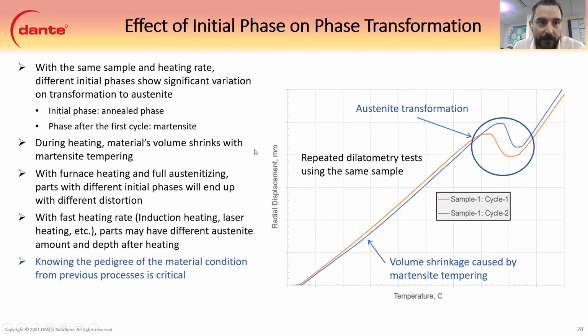And so during this, the initial phase was an annealed phase here as it comes through the first cycle. And we see our austenite start happens at whatever temperature this is, and it finishes here. And then when we come through again, we now have martensite. And so martensite needs to temper. The carbon atoms need to come out of the lattice, and you have a volume shrinkage here as you're tempering the martensite. And then that changes where your austenite formation is. You can see it's further at a higher temperature. It's further on down the line here. And that's really important to know, and that's why we usually run a dilatometry test a couple times in order to get that data.